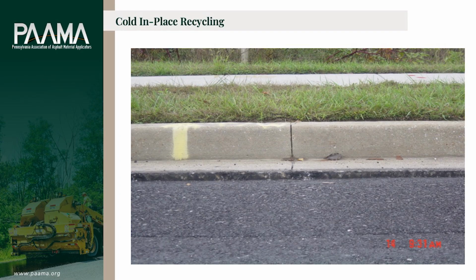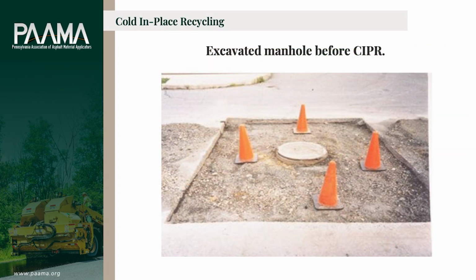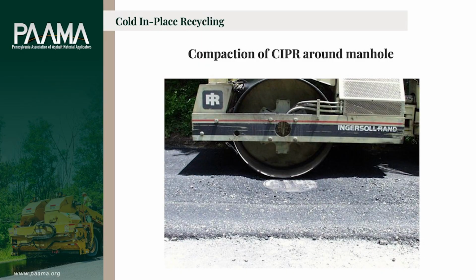Utilities, as I said, we've got to box them out. You either have a 10 or a 12-foot cutting mandrel. So what happens is the big machine will come to the edge of the cutout. We will lift the cutting mandrel, walk across the utility, sit down again, and continue recycling. And as the paver comes through this area, it'll place all that new recycled mix in and around the utility, and then it will get compacted. Don't raise your manholes or your water valves until the recycling's completed, and that way you can raise them to the depth of the new hot mix, whether that's, as I said, a chip seal or a hot mix asphalt or any other type of wearing surface.